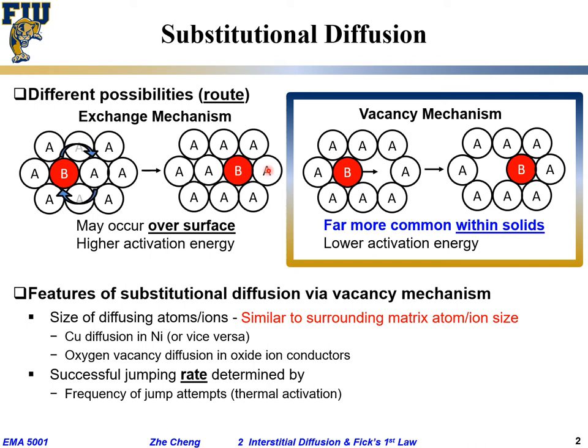So in order for the vacancy mechanism to work, for the atom to move, it also needs a so-called nearby vacancy. The higher the vacancy concentration, the more likely one is surrounded by at least one vacancy. Make sense? And the vacancy concentration, from what you learn in thermodynamics, is determined first by temperature. Typically, the higher the temperature, the more the vacancies, but also by so-called intentional doping.